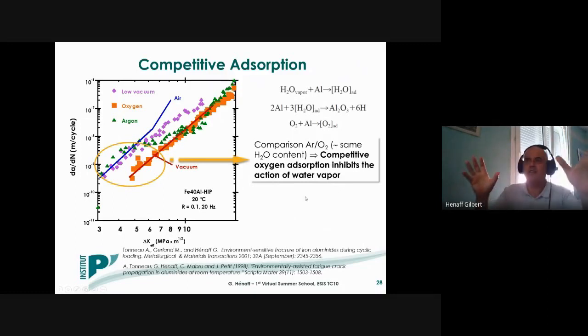Just to mention that in some cases, here in the case of iron aluminides, you can have a competitive adsorption between water vapor and oxygen, as described by these equations. And the point is that in that case, in an oxygen atmosphere containing some traces of water vapor, this competitive adsorption process leads to the fact that the fatigue crack growth rates obtained in this oxygen atmosphere are similar to the one obtained in vacuum, while, for instance, in argon, with the same water vapor content, in a low delta K region, we have almost the same fatigue crack growth rates as in air. So again, here we have a beneficial effect of this competitive oxygen adsorption process.